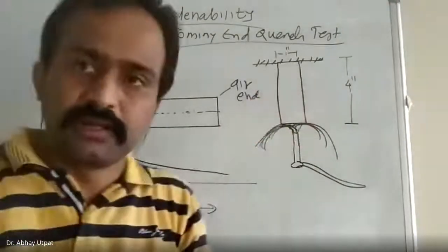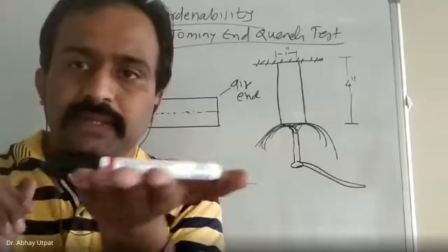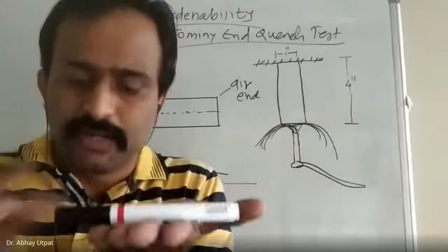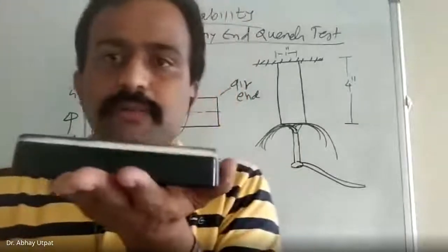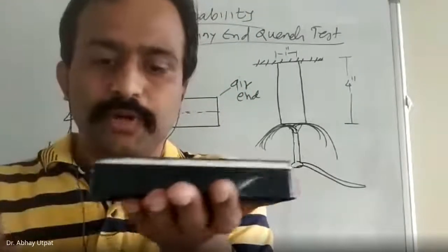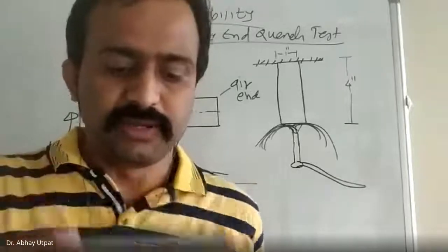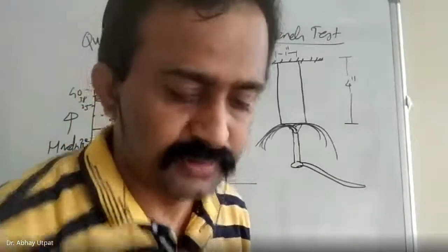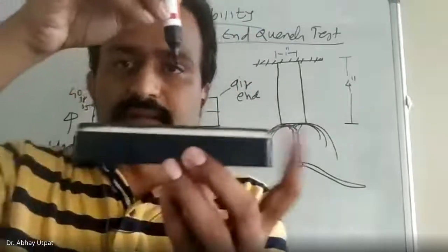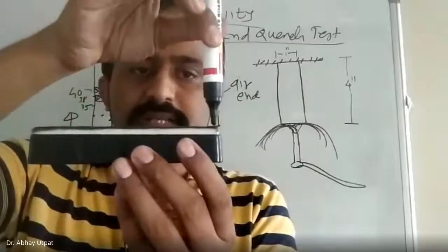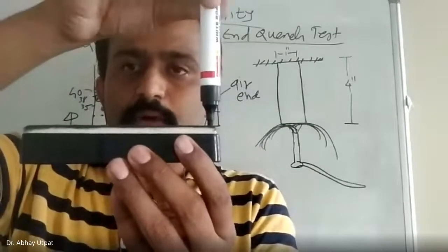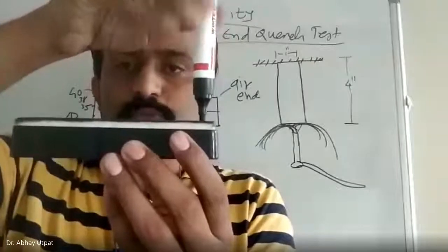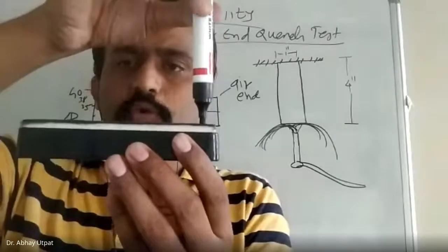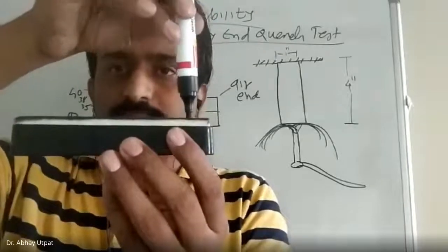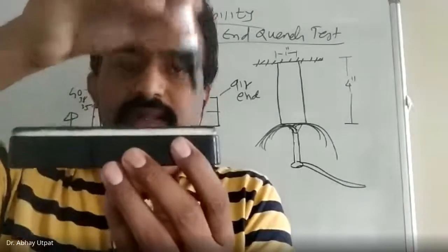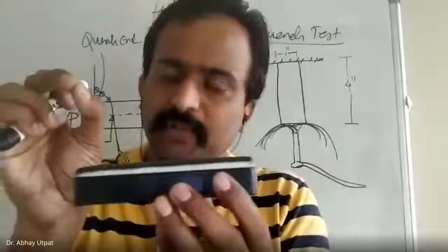This bar is taken and put on the hardness testing machine. In the same way, there is a pad on the hardness testing machine. Assume that this is your component. Just see now. This is your component, and this hardness testing machine has the tip or diamond. So this is quench end and this is air end. I measure the hardness here at this point. I got 40 RC. Immediately I go to the next point, just 1 mm distance. I got 39. Immediately third point, I got hardness 38. The distance between each point is 1 mm, not more than that.